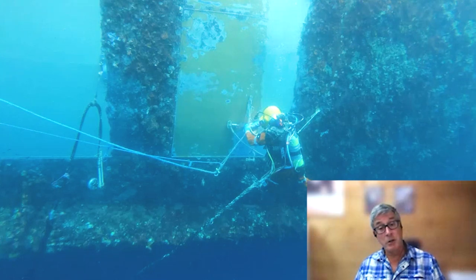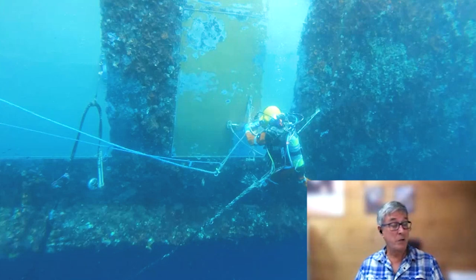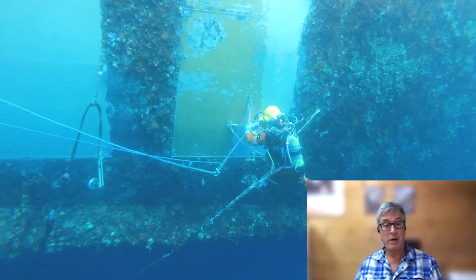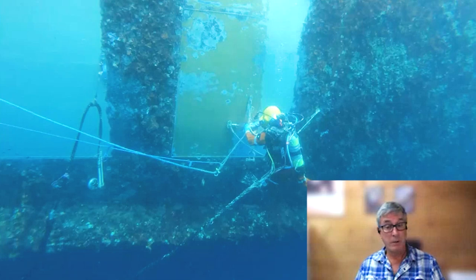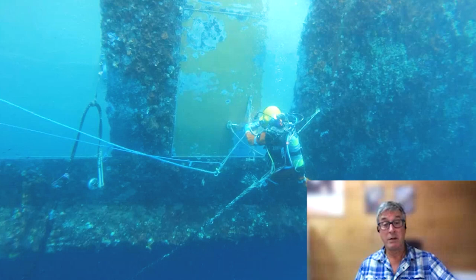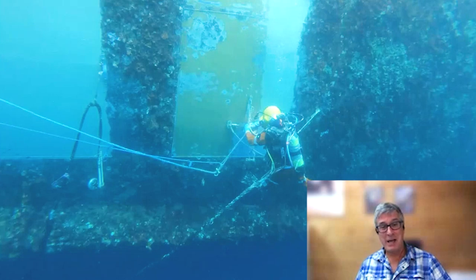We always put a second coat on simply because it fills the troughs left behind. It's not a dead flat surface when we finish painting. And if it fills the troughs, then you're guaranteed to be well over 300 to 400 microns when you've completed the work. And that means all the thin areas the guy might leave. Nobody's perfect. So far, on all the work we've done, we haven't had any holidays.